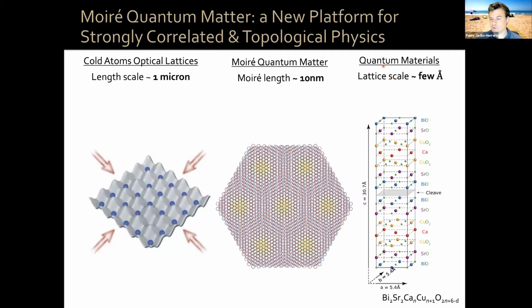This is a nice complement to our other two platforms for this type of physics. One is actual quantum materials, with a lattice scale of a few angstroms. The other is ultracold atoms in optical lattices with a typical length scale of about a micron. These two platforms have existed, one for many decades, the other for about 2 decades. In the past few years, we have this Moire quantum matter, where the natural length scale is intermediate between these other two platforms, around 10 nanometers.